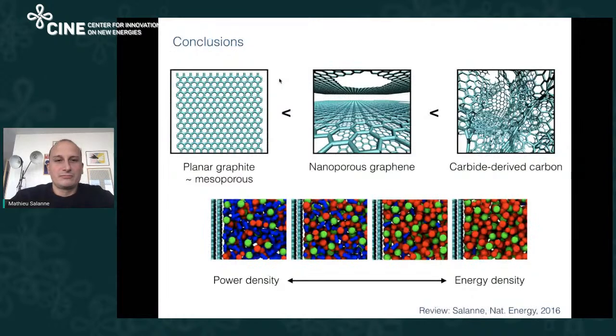So to conclude this talk, I hope it was not too long. Now we have a good idea that planar graphite does not have a good capacitance, but this was expected. But then in the case of nanoporous materials, having a pore size distribution seems to be very important to increase the capacitance of the system, and maybe graphene is not so good, or we should be able to have graphene with pore size distribution, which can be quite tricky to do.